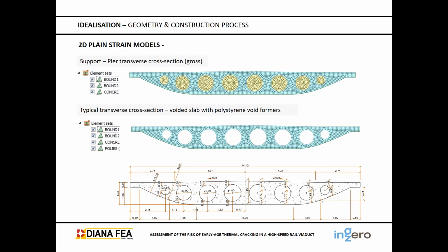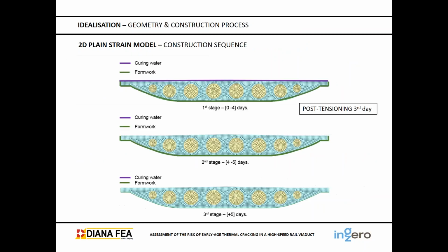We propose, first of all, to do plane strain models, one from the support or the pier transverse cross section, and the other from the voided slab with the polystyrene void formers. What is the construction sequence of these models? We have the first stage, which is